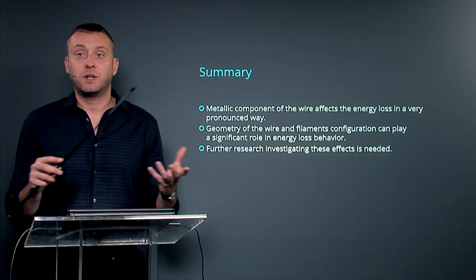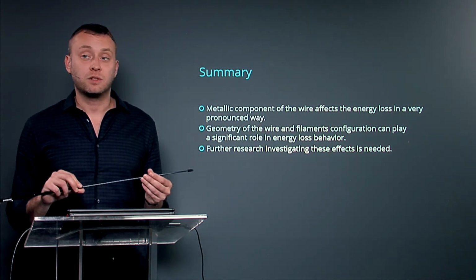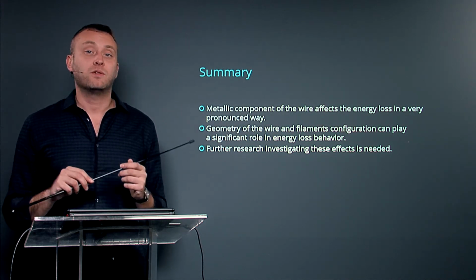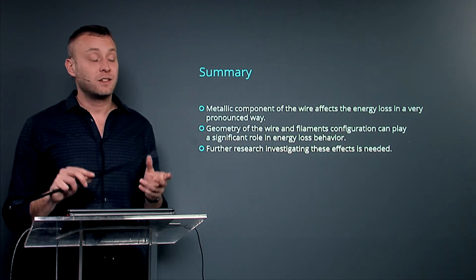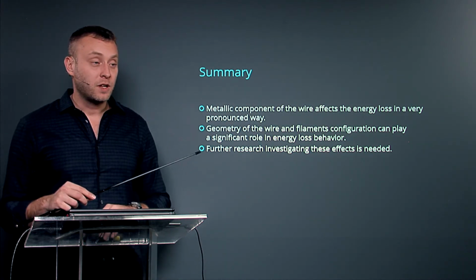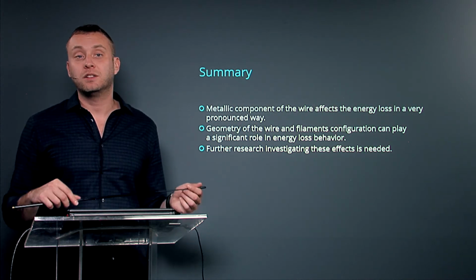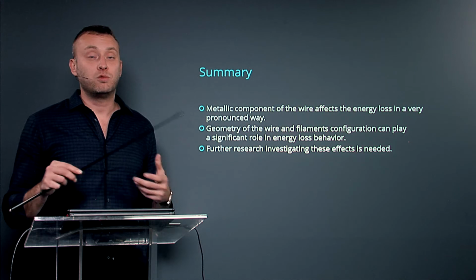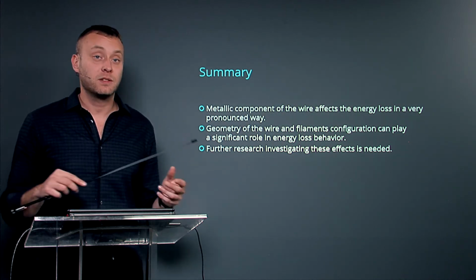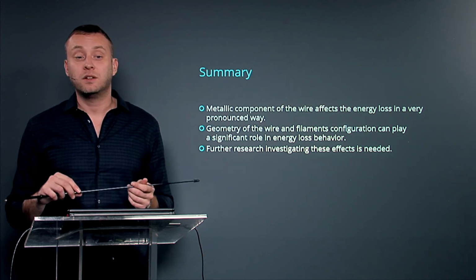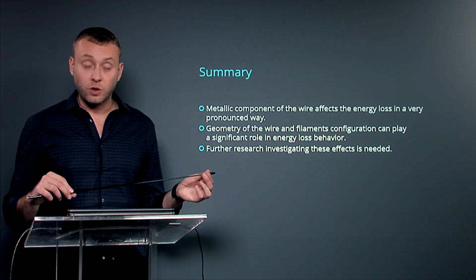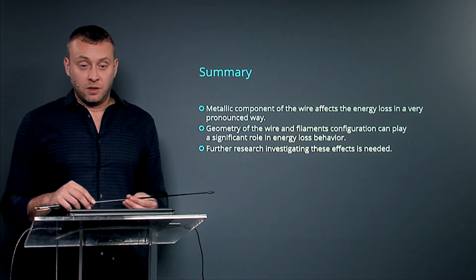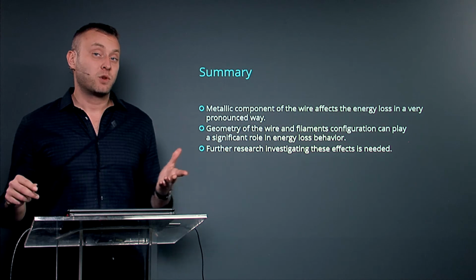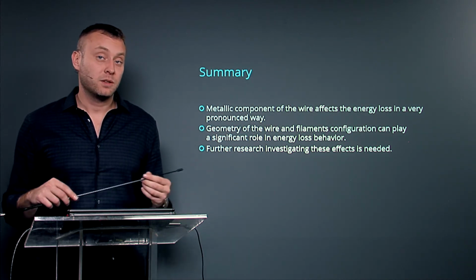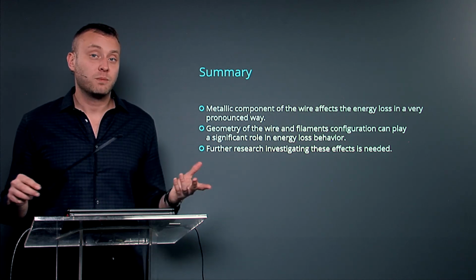Because of these new discoveries, we have to take the metallic part of the superconducting wire into account. So the properties of the metallic material of the wire play a significant role in the energy losses. So we have to conduct additional experiments to redesign our experiment and the measurement techniques to take this into account, which is not an easy task, I have to say, because this material cannot be separated from the wire, from the superconducting material. It's virtually impossible to do.